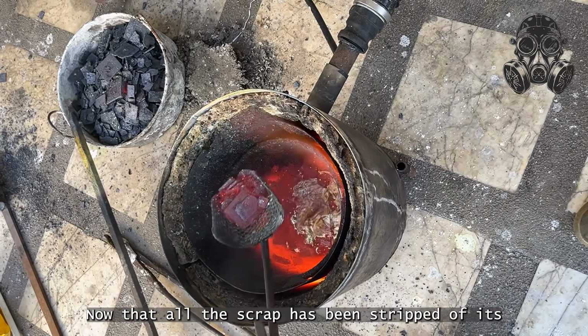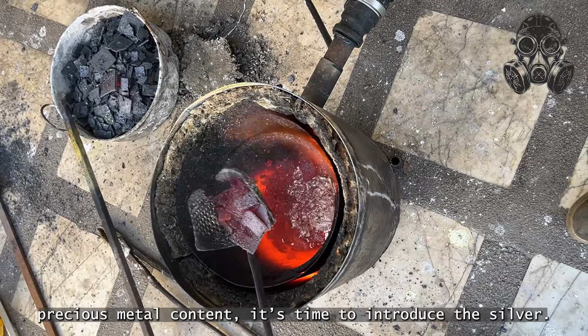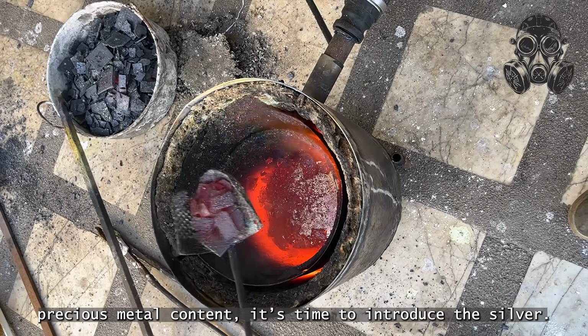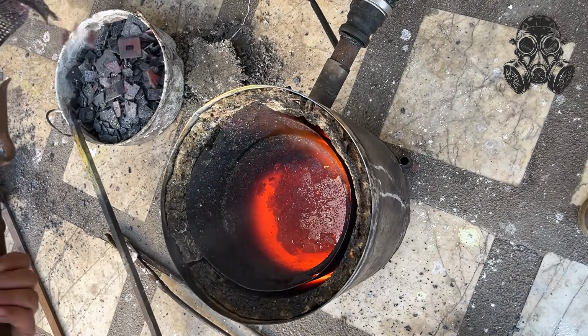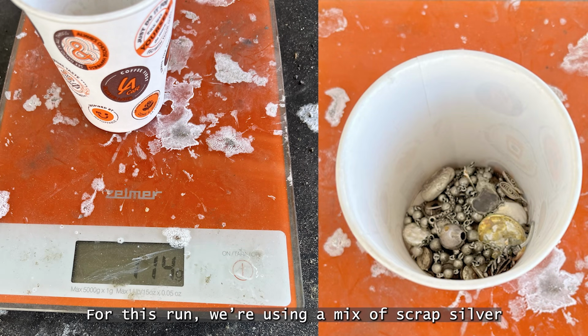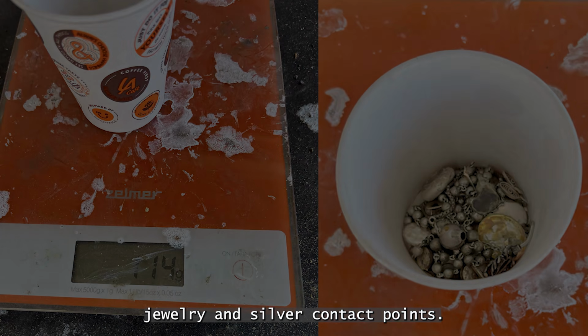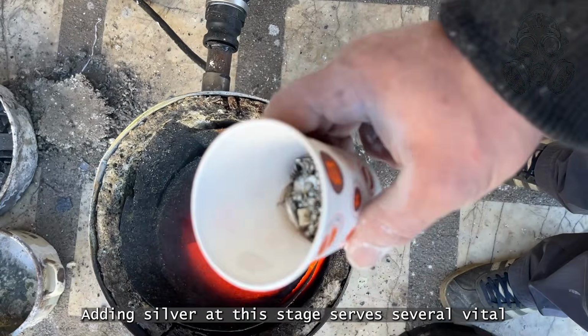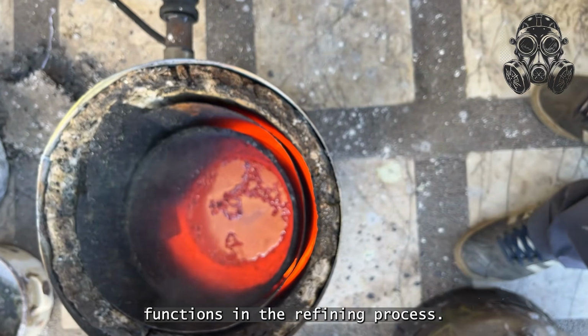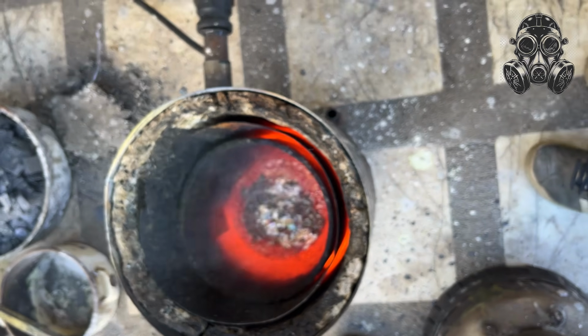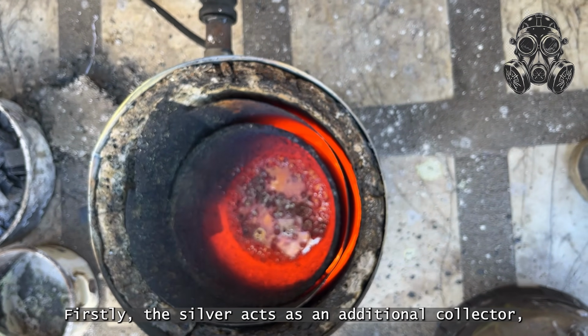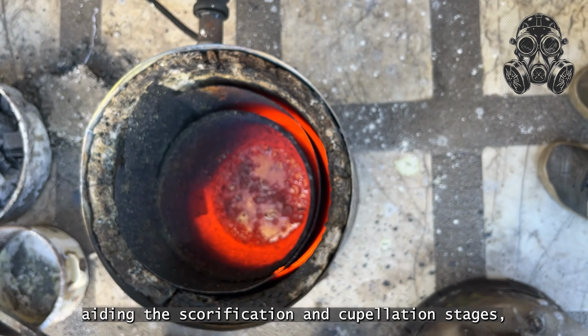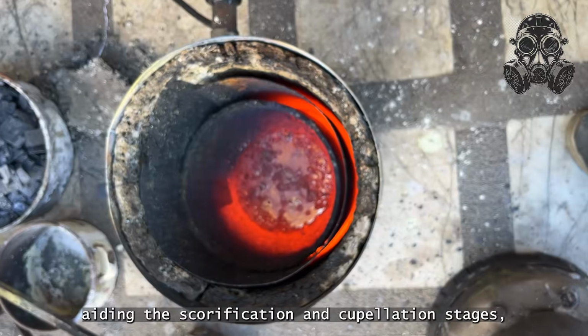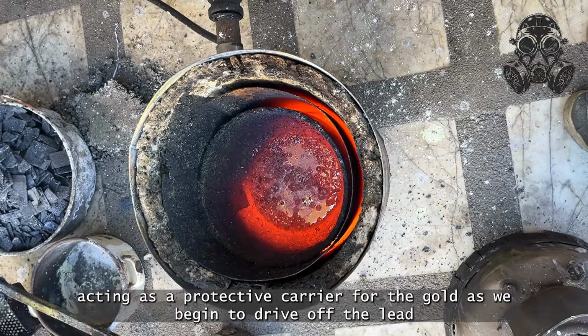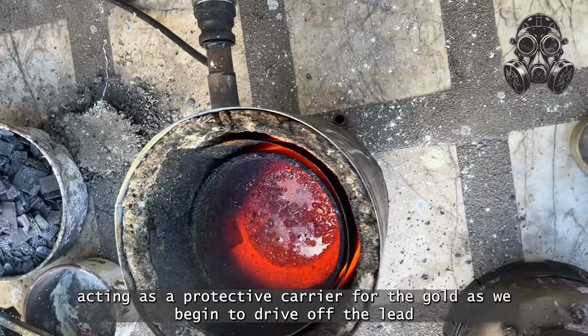Now that all the scrap has been stripped of its precious metal content, it's time to introduce the silver. For this run, we're using a mix of scrap silver jewelry and silver contact points. Adding silver at this stage serves several vital functions in the refining process. Firstly, the silver acts as an additional collector, aiding the scorification and cupellation stages, acting as a protective carrier for the gold as we begin to drive off the lead.